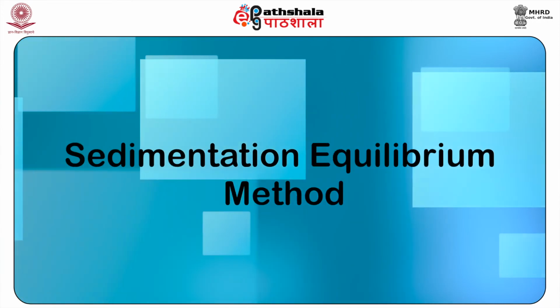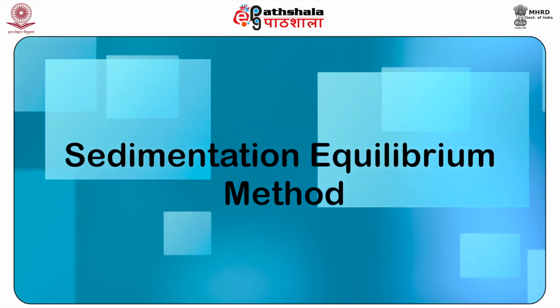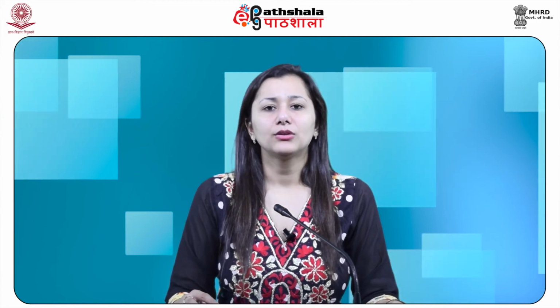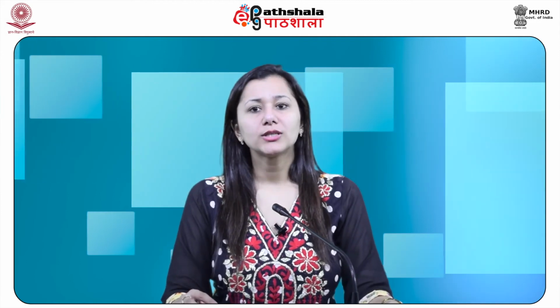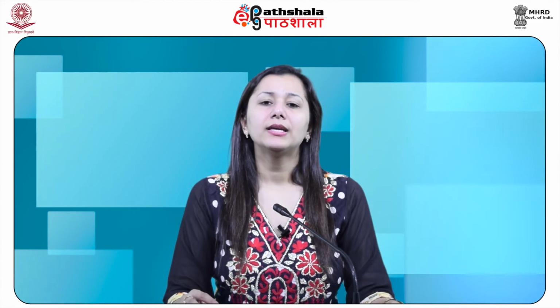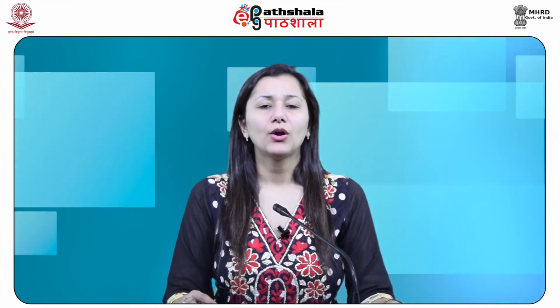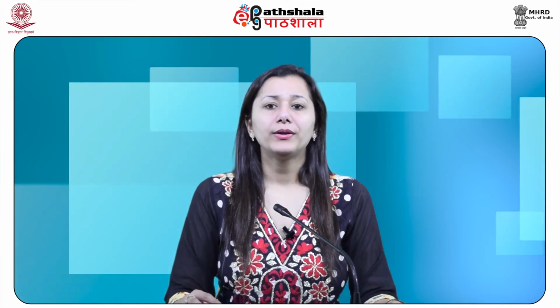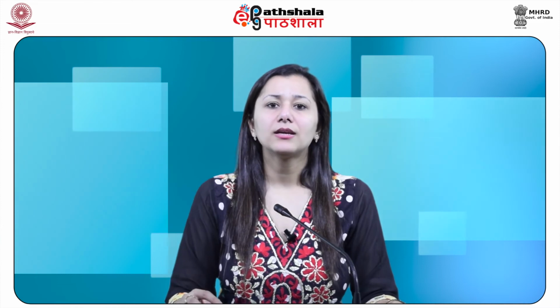Now we shall have a look at the second method, which is the sedimentation equilibrium method. In the sedimentation equilibrium method, the rotor speed is lower, about 10,000 rpm, than in the sedimentation velocity method, where the rotor speed was of the order of 60,000 rpm. When an equilibrium between sedimentation and diffusion is reached, there is no net flow.